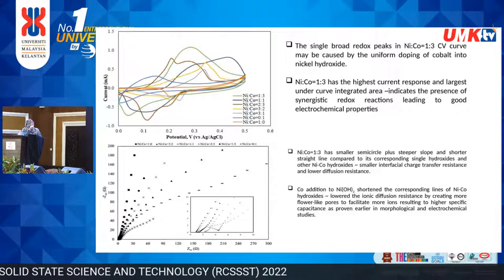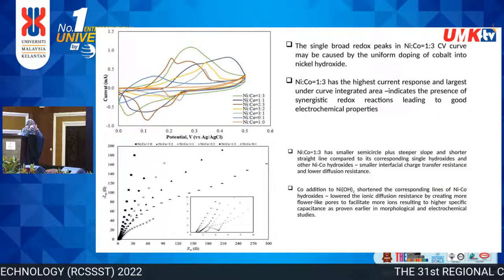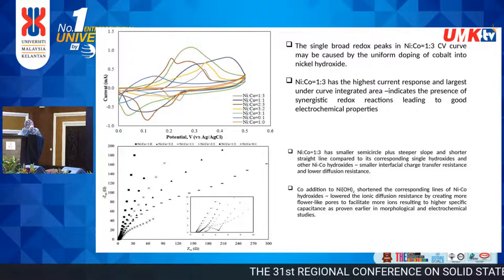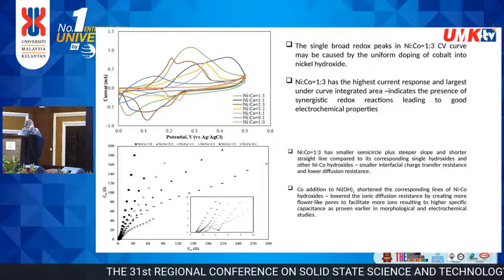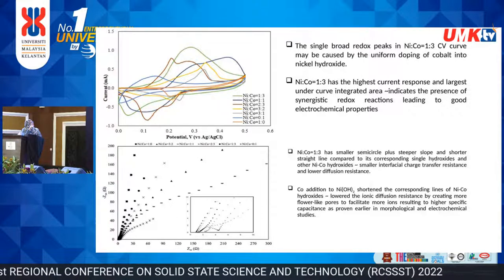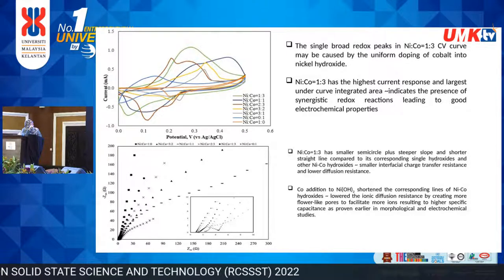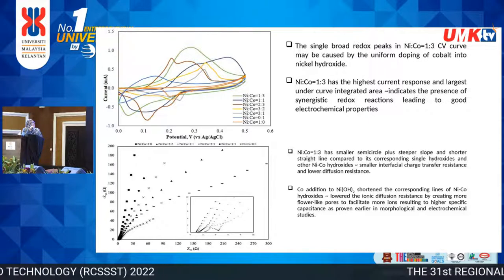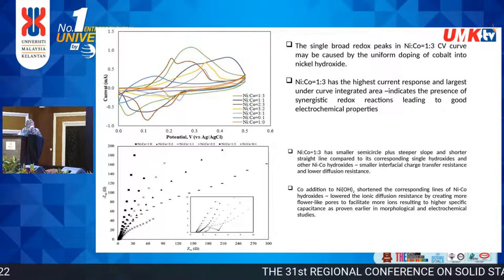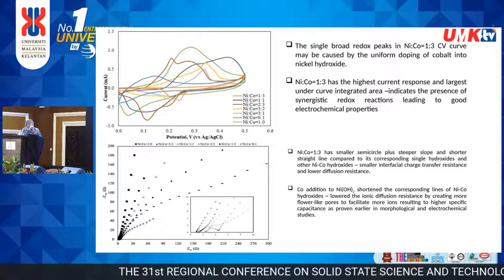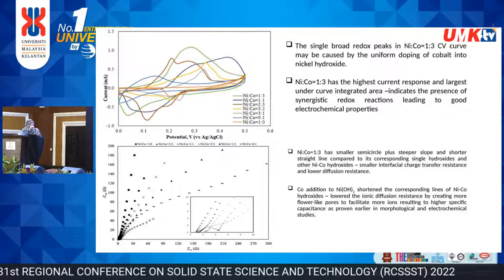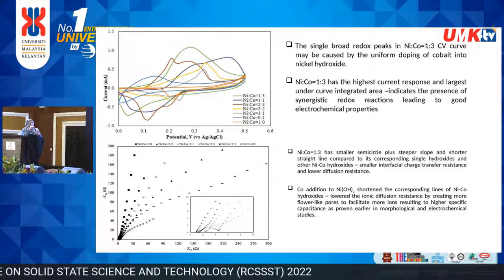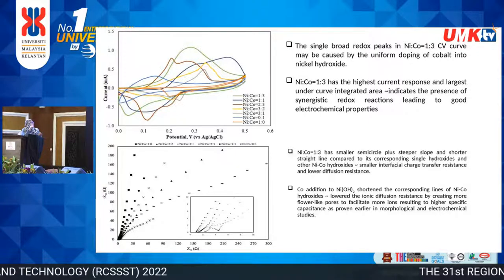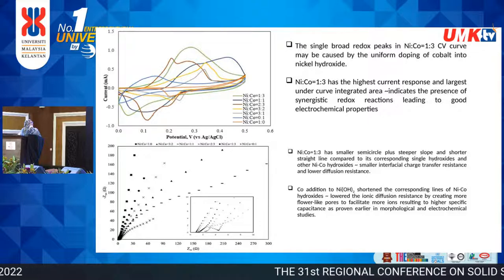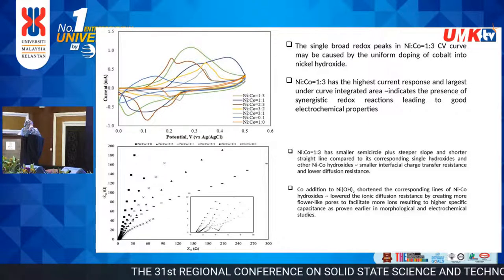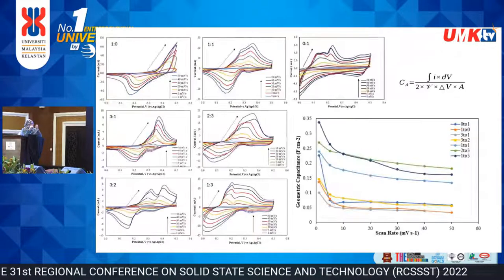Okay, this is the cyclic voltammetry. The single redox peak curve may be caused by the uniform doping of cobalt into nickel hydroxide. Nickel cobalt 1-3, the green one there, has the highest current response and largest under-curve integrated area, indicating the presence of synergistic redox reaction leading to good electrochemical properties. Okay, this is the EIS. Nickel cobalt 1-3 also has the smallest semicircle, indicating that it has small charge transfer resistance.